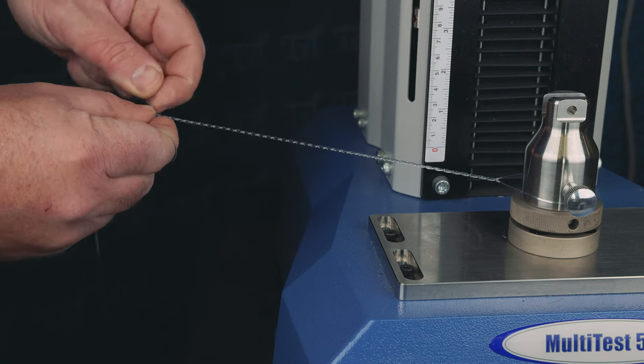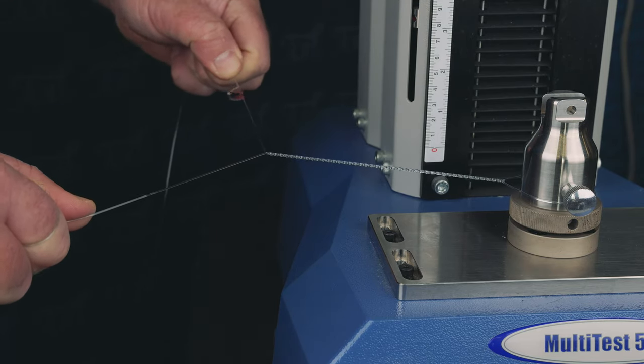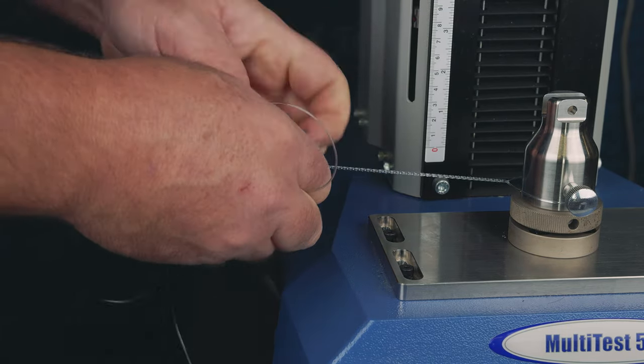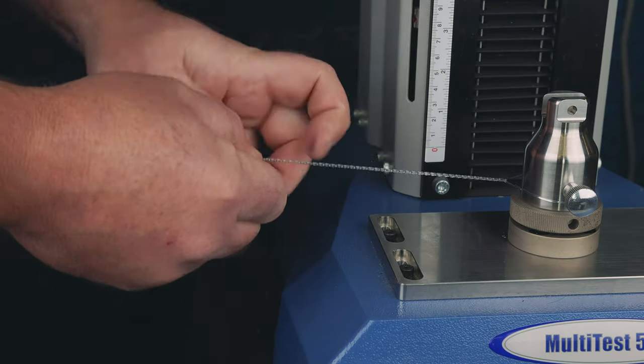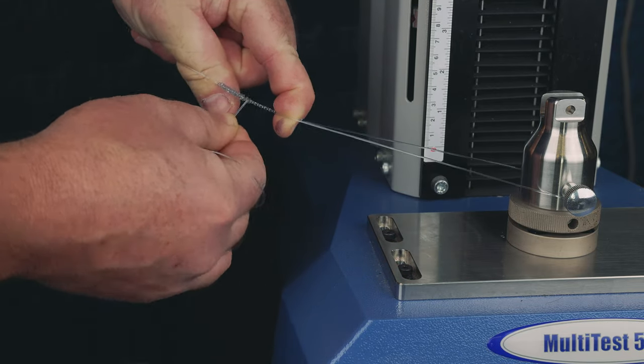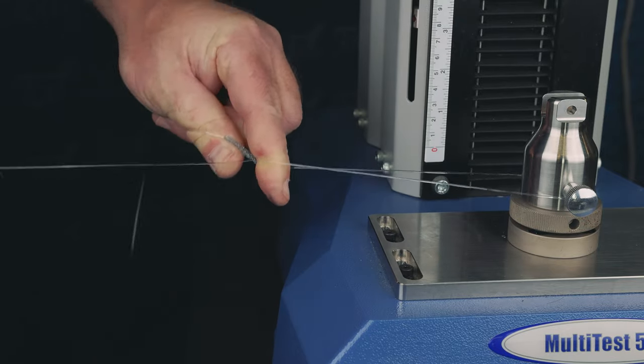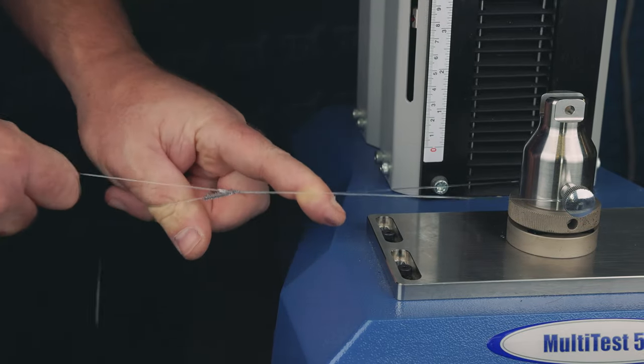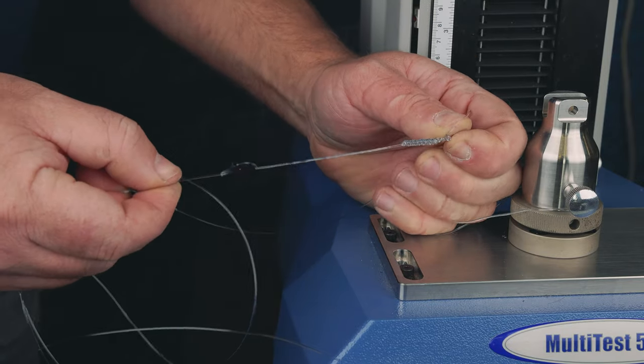At the point of pushing the twists tightly together, those twists generate an awful amount of heat and friction when you start to compact them down. The damage to the main line actually occurred here, but the knot is already three inches away from where you damaged it. For all intents and purposes the damage is negligible because we've seen how strong the knot is, but it does explain why the knot fails where it does — a few inches up.